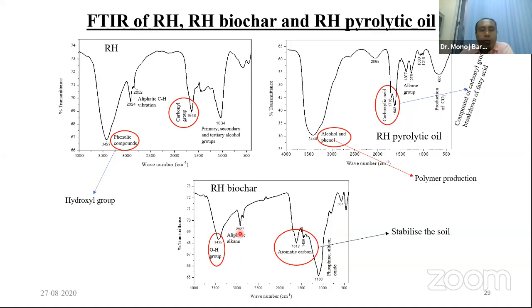Also, the peaks found at 2900 indicate the presence of aliphatic group, and most importantly, in the biochar, the peaks found at around 1600 and 1456 indicate the presence of aromatic compound, which is very important, because if we get some aromatic compound in the biochar, and if we apply this kind of biochar for agricultural purpose, like improvement of the soils, that will be very useful, because this aromatic carbon kind of compound stabilizes the soil composition.